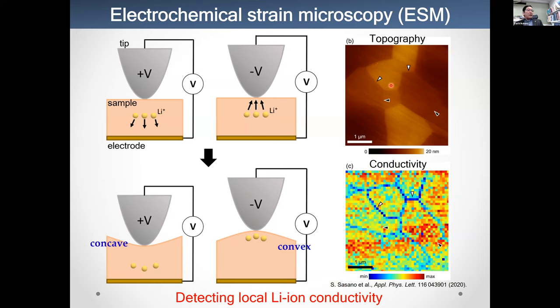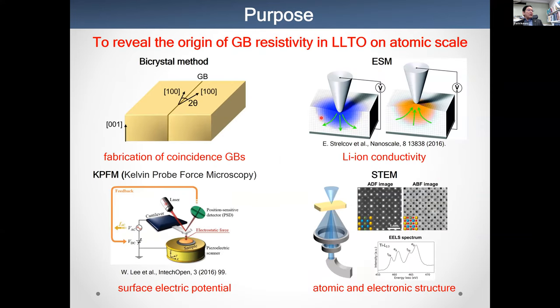This is a case of polycrystalline materials. You can see most boundaries have low conductivity, but some boundaries, indicated by these black arrows, which are actually sigma 5, have a conductivity almost similar to the grain interior. So this is a very powerful technique to see the local ion conductivity. In this study, we fabricate bicrystals and apply the ESM technique. We also apply the STEM imaging technique for atomic resolution characterization. And KPFM, Kelvin probe force microscopy, is also applied to investigate the surface electric potential. We use this kind of procedure.